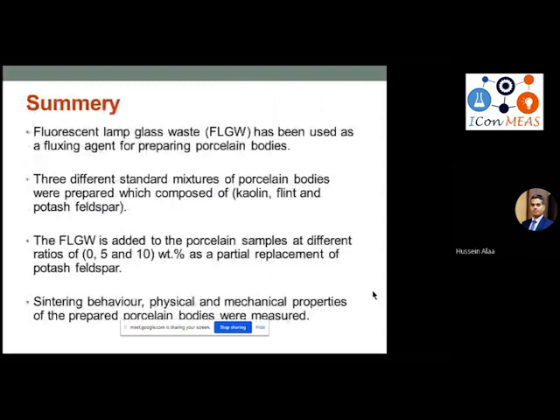Summary: fluorescent lamp glass waste, FLGW, has been used as a fluxing agent for preparing porcelain bodies. Three different standard mixtures of porcelain bodies were prepared, composed of kaolin, flint, and potash feldspar. The FLGW is added to the porcelain samples at different ratios of 0, 5, and 10 weight% as a partial replacement of potash feldspar. Sintering behavior, physical, and mechanical properties of the prepared porcelain were measured.